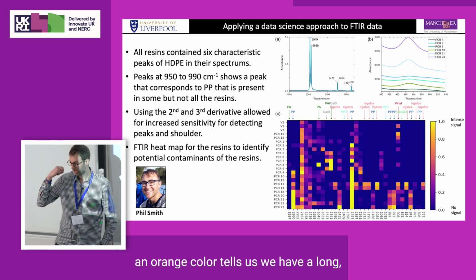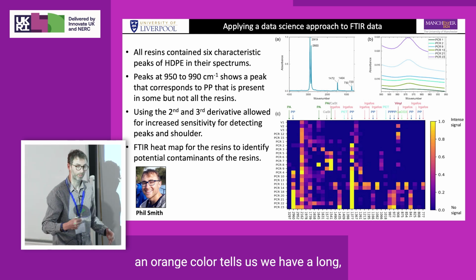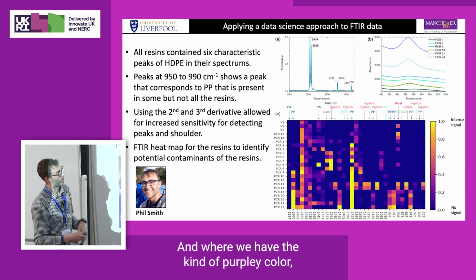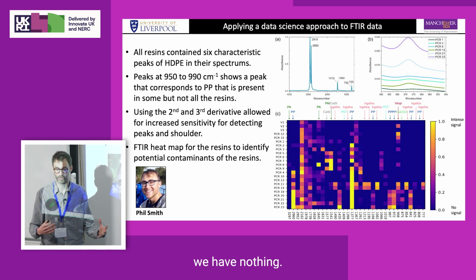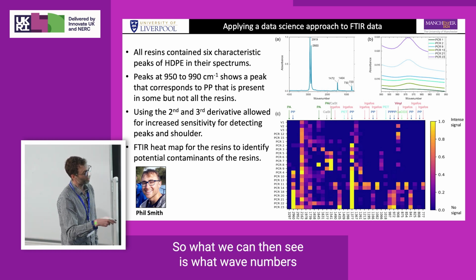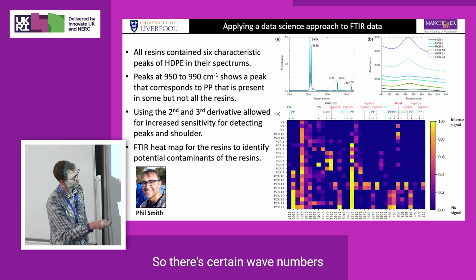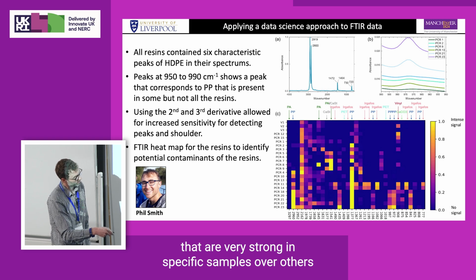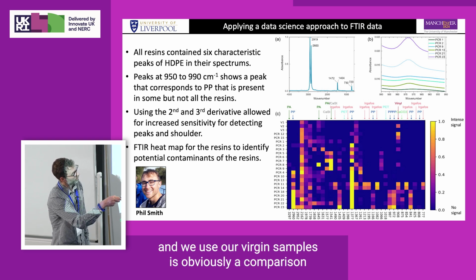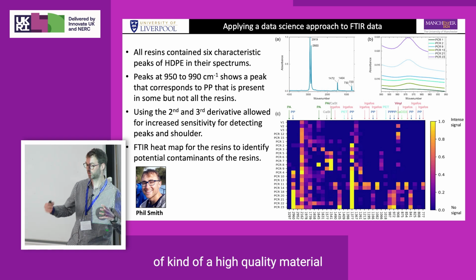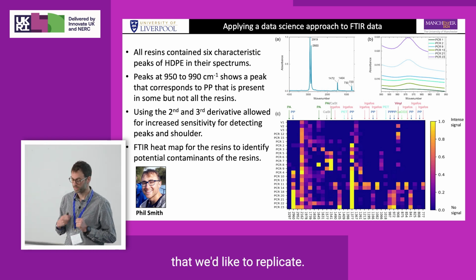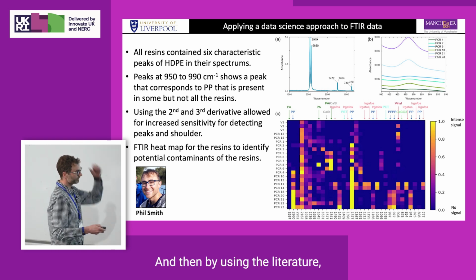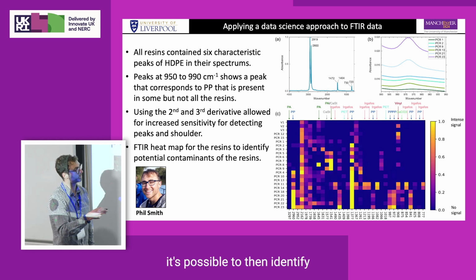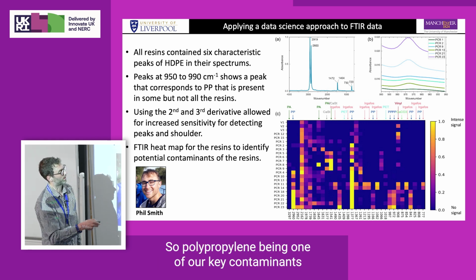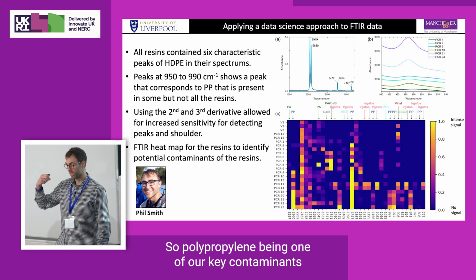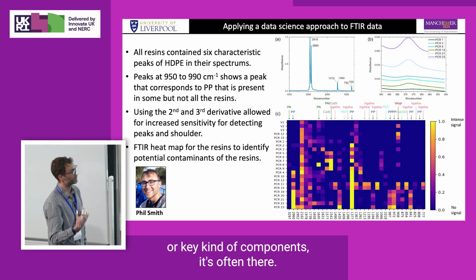Where we have an orange color, we have a large signal there, and where we have the purply color, we have nothing. So what we can then see is what wave numbers help us differentiate samples. There are certain wave numbers that are very strong in specific samples over others, and we use our virgin samples as a comparison of a high quality material that we'd like to replicate. Then by using the literature, it's possible to identify what some of these things are. Polypropylene is one of our key contaminants, or key components that's often there.